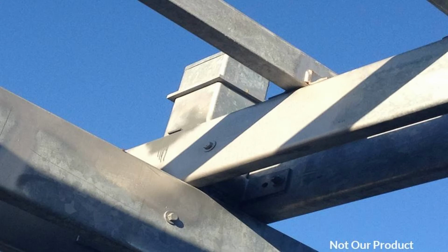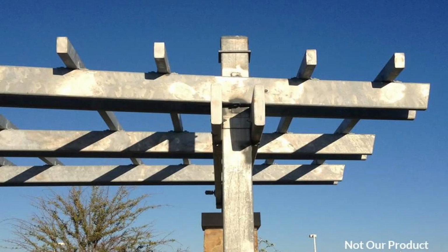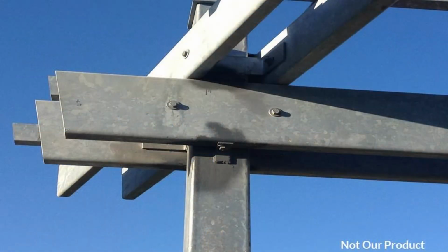Here, you can see the patina of the galvanize and also the cold zinc spray that was applied where the galvanize was burned off during the process of welding in the field. Eventually, this structure will show signs of rust, and that rust will drip onto the finished surface below. This trellis system could have been fabricated out of mill-finished aluminum, and rusting would not have been a concern. Here is another close-up image of that same trellis system.